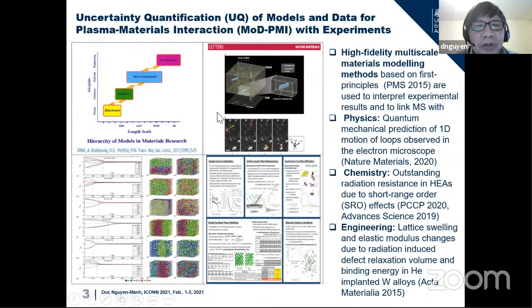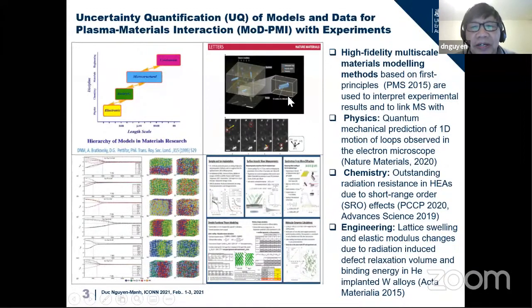In this slide, we show that in the last few years it is possible to use this scheme to link with physics. We predicted the motion of a one-dimensional dislocation loop moving in irradiated materials by quantum mechanics prediction, which was published in Nature Materials last year. We were also able to predict the outstanding radiation resistance due to the short range order parameters in the high entropy alloy, and Los Alamos laboratory detected the same material to be very radiation resistant.